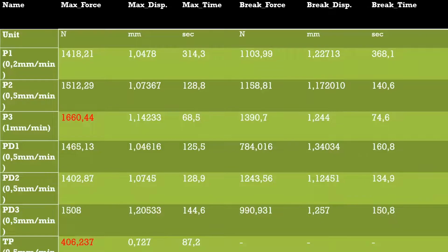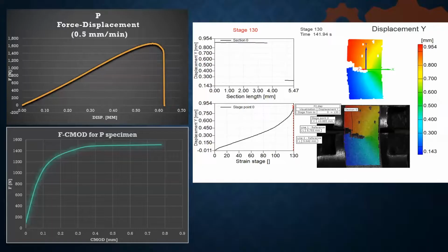After examining the samples, the following results were obtained. The values obtained on the universal testing machine are shown in the table, but I would focus on diagrams. One of the parameters for characterizing fracture mechanics are the CMOD and CTOD, which were obtained in this case with the help of the Aramis system by giving a point-point distance command in the software. In this way, it is possible to monitor the movement of two points on the recorded sample during the test. The points are placed at the very beginning of the groove, as well as the very end of the crack, from which the CTOD value was obtained.